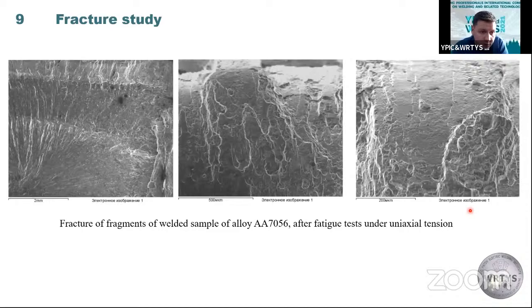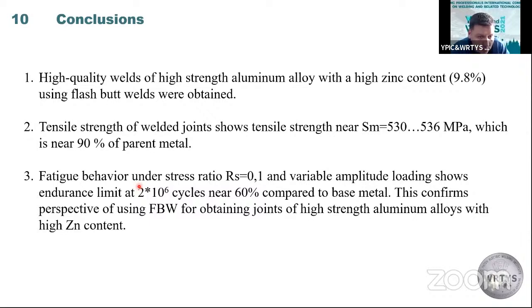After this, we provide a fracture study and an investigation of the fracture cross section. We can see that the stage of fatigue crack growth to the stage of fracture is more than for crack initiation. Joints of high strength aluminum alloy with high zinc content can be obtained using flash butt welds.